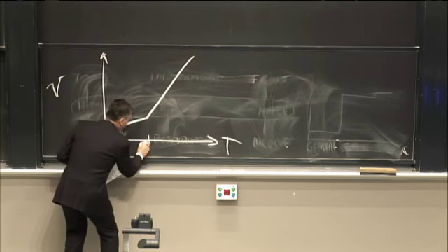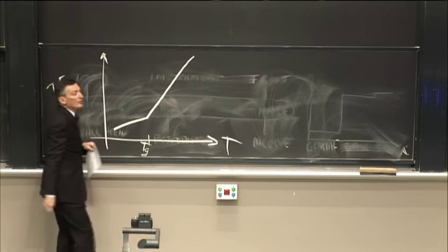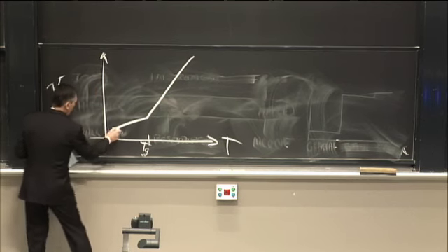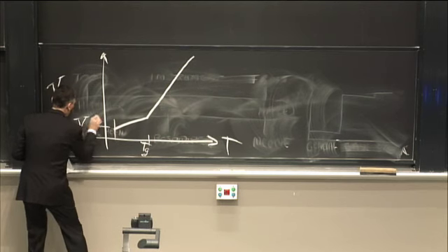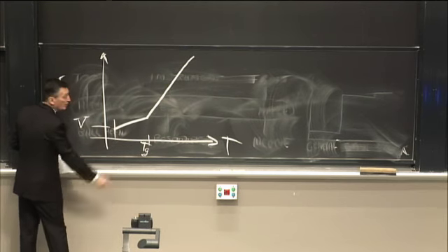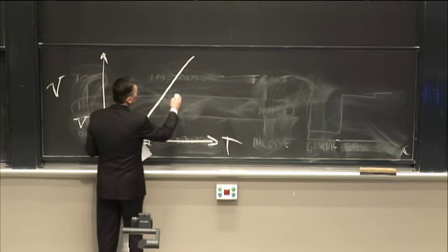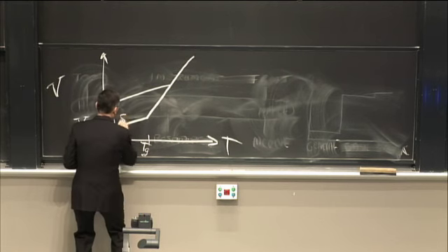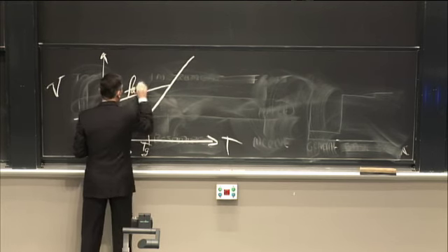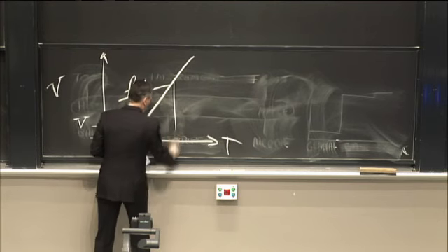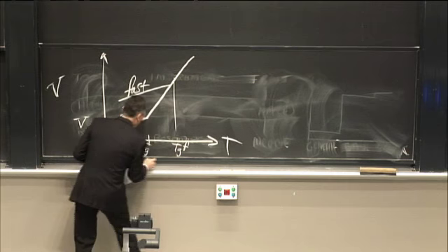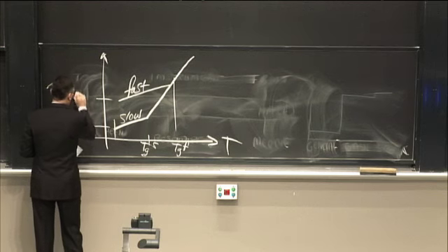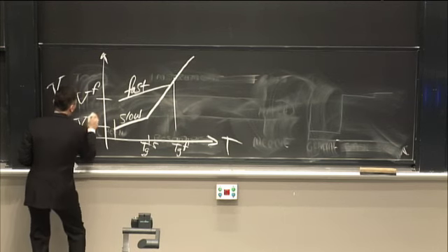This is the solidification temperature, which in the case of liquid to amorphous solid is the glass transition temperature. And here we have the excess volume. This is the volume, and then there's some crystalline volume and so on. I can cool at a different rate, and I get this. So this is slow cool. This is fast cool. Well, we have a Tg up here. Tg fast, I'll call it, and Tg slow. So that'll give me a different volume. So this is volume fast and volume slow.